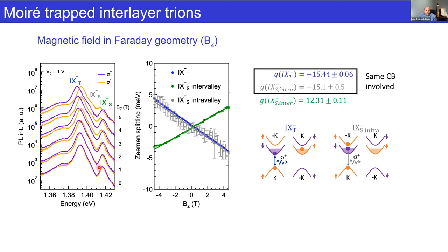So you can see the triplet states shift together in the opposite direction of the singlet state, and it gives opposite g-factors, suggesting again that the same conduction band is involved. So we think we can identify these different species, and maybe it's worth revisiting some of these other publications that have multi-peak spectra. Perhaps the peak assignment of those publications could be revisited using this knowledge from the magneto-optics, and it also highlights the importance of a gate-tunable device.